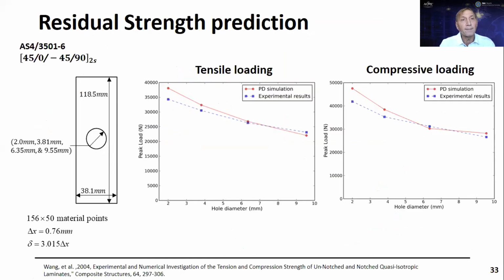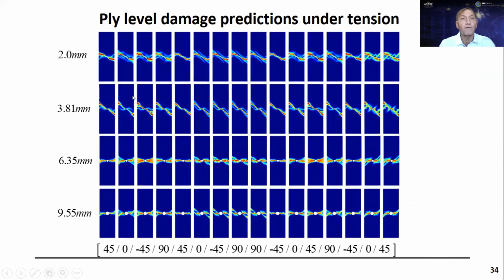So here we have this laminate. It's a graphite epoxy, it's quasi-isotropic. The hole size varies between 2 to 9.55 millimeter. And this specimen is subjected to tensile loading and compressive loading. You can see the failure stress, the experimental results and the peridynamic simulations here, depending on the hole size. But what's interesting here is if I look at the tensile loading and for a range of these hole sizes, this is under tension, it's the ply level damage, matrix damage.